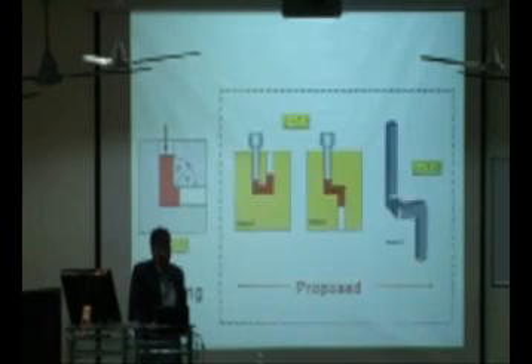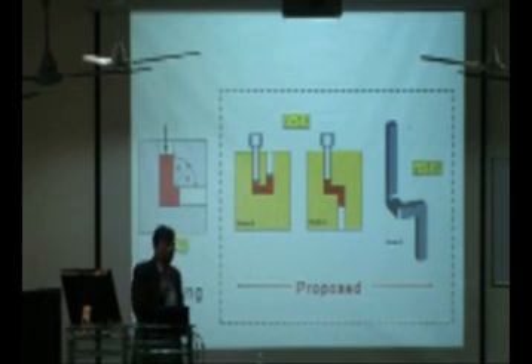But the problem is this: the technique is very good and well established, but it has not been commercialized till yet. The reason is that it is a batch process, because again and again the same thing has to be done. So it is very difficult for a manufacturing industry because a good amount of time is required. There has to be some technique by which we can make this process continuous, so that in one go you can achieve all 5 passes.